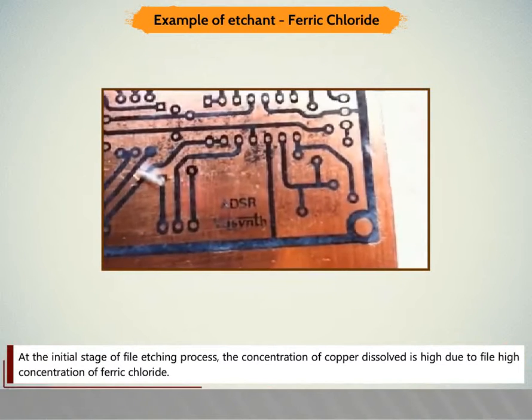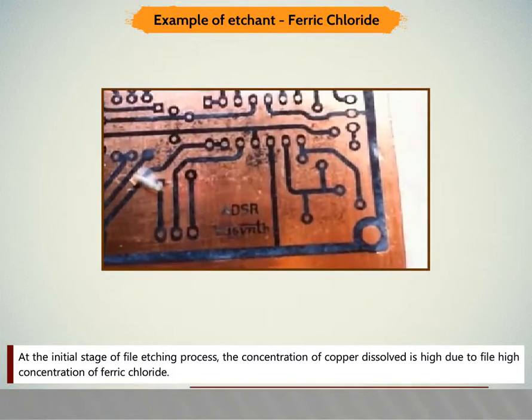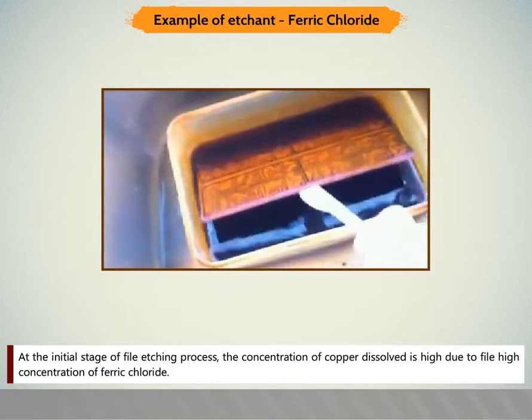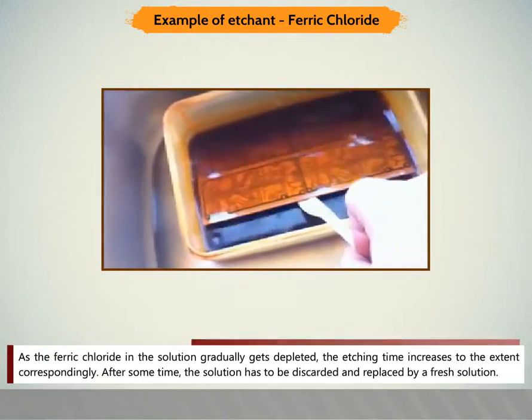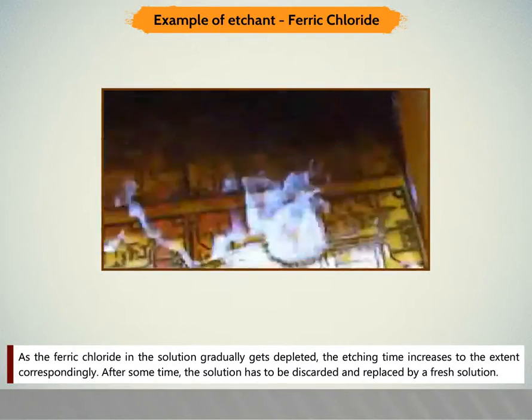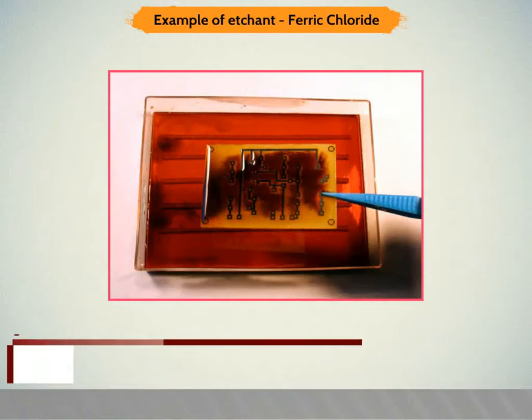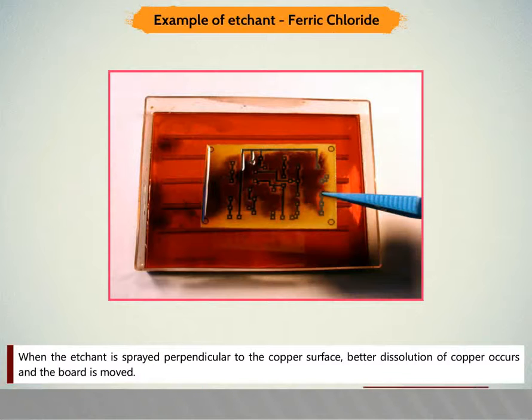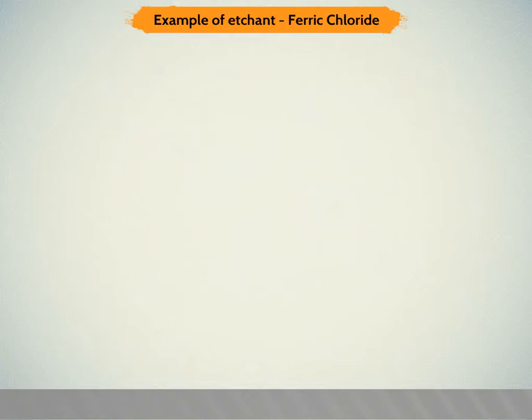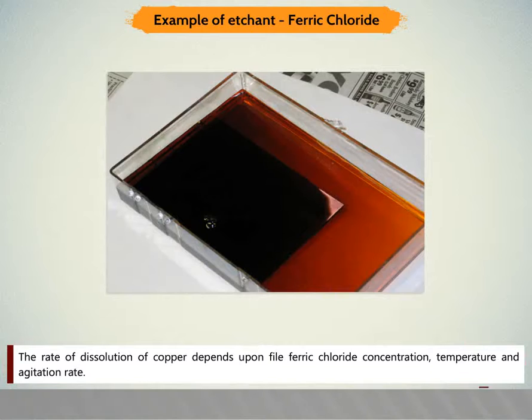At the initial stage of the etching process, the concentration of copper dissolved is high due to the high concentration of ferric chloride. As the ferric chloride in the solution gradually gets depleted, the etching time increases correspondingly. After some time, the solution has to be discarded and replaced by a fresh solution. When the etchant is sprayed perpendicular to the copper surface, better dissolution of copper occurs and the board is moved. The rate of dissolution of copper depends upon the ferric chloride concentration, temperature and agitation rate.